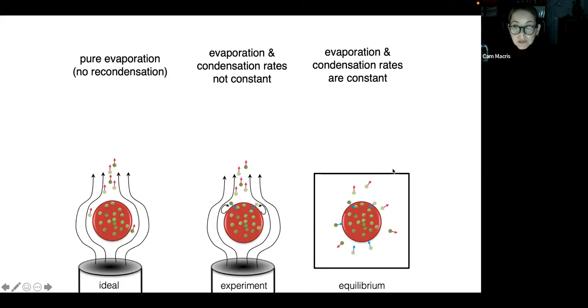On the other end of this spectrum, you've got a situation where you have equilibrium between the gas and the vapor, meaning that the evaporation and condensation rates are constant. And this would exist in a closed system where you don't have material escaping. Our experiments are somewhere in the middle of these two end members, as shown in this middle cartoon. And what we see here is that there is a return flux where some of the evaporated particles are returned to the melt and recondense, while some are carried away. And then in this scenario, the evaporation and condensation rates are not constant.